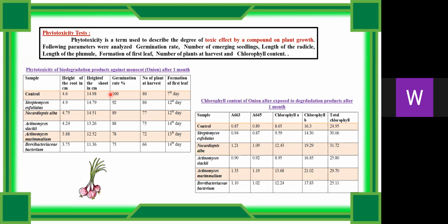in order to assess the influence of the biodegraded products on the normal growth of the plants. The control showed a good height, root and germination rate. At the same time, our actinomycete strains also showed significant growth and germination rate, suggesting that there is no adverse impact on the growth of the plant. Followed by the chlorophyll content, you have a maximum chlorophyll content compared to the control. It indicates that significantly less toxicity was observed.